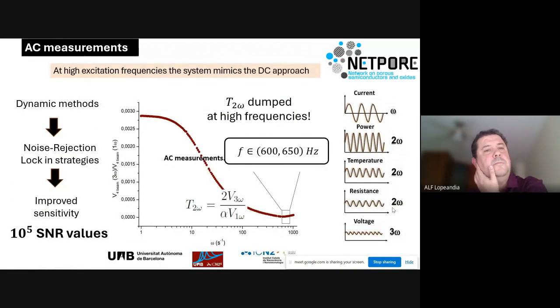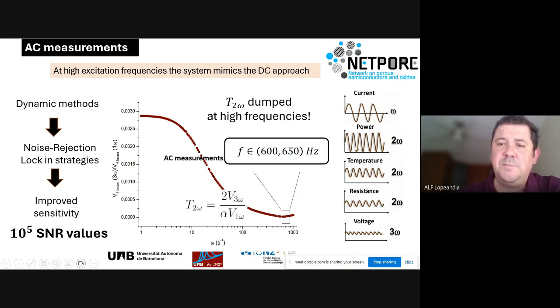These structures are very similar to the ones that were defined by Li Shi. Maybe there is some difference in terms of geometry, but the main difference of our approach is that we will use high frequency excitations in order to mimic the DC approach. If we heat the system with an AC current, typically we release power at 2 omega. We heat with a sinusoidal signal at the fundamental frequency. We heat up the system at 2 omega, and typically we have a temperature oscillation at 2 omega. But this temperature oscillation is damped by the heat capacity of the system.